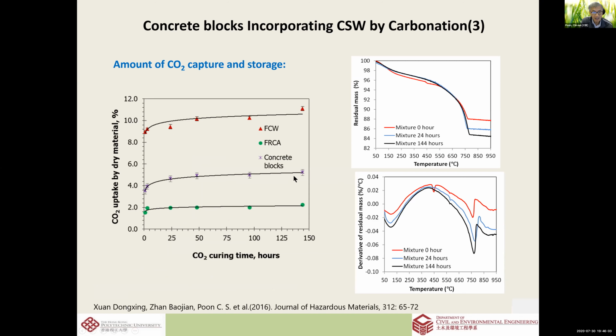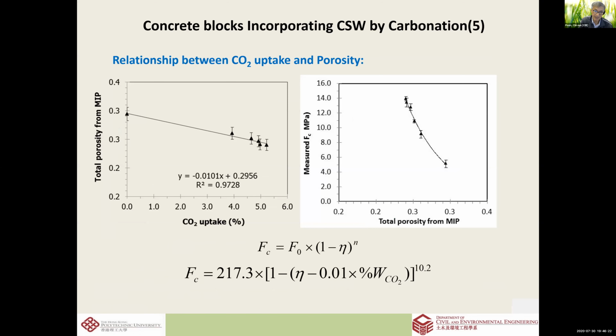This could also take up about 5% of CO2. This is the CO2 uptake by the concrete slurry waste itself, but after mixing with the recycled aggregate, it also takes up CO2. After mixing, the CO2 uptake is less, but it still takes up 5% CO2. I think I skipped that.